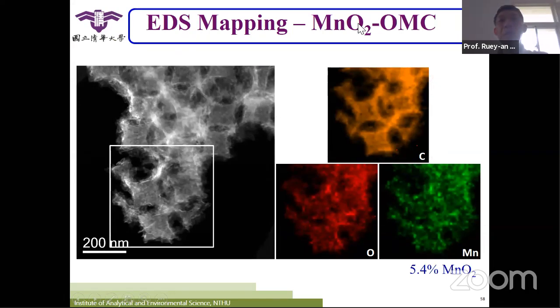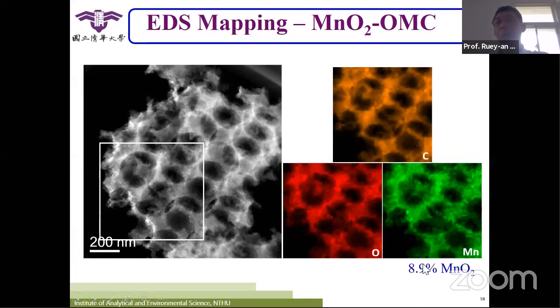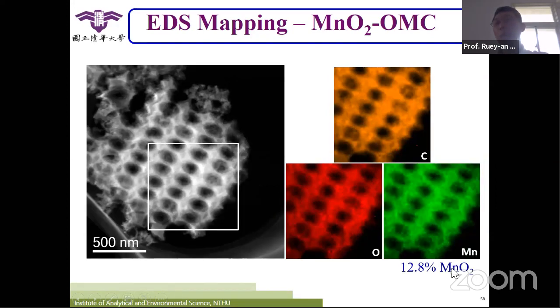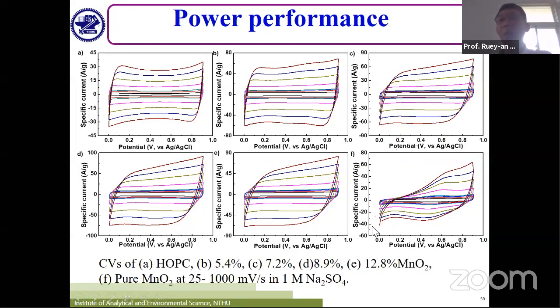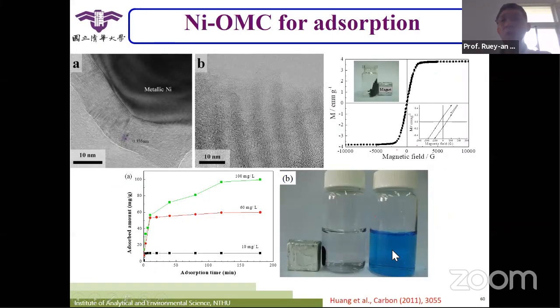Using EDS mapping on the highly ordered mesoporous carbon with MnO2, when we add 5.4 weight percent of MnO2, the case is here. 8.9 is here. 12.8 weight percent of MnO2 is here. You will always see that carbon, oxygen, and manganese are all distributed the same way, which means our MnO2 is homogeneously inside the OMC. So we can get quite good electrochemical properties, and it can also be used to remove dye. So we can recover the loss with highly ordered mesoporous carbon here.